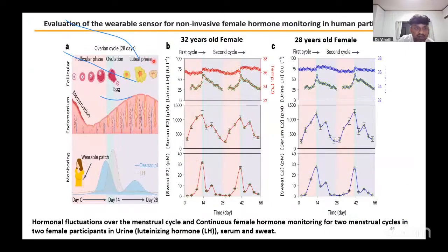Here from the real samples we can identify the growth of female hormone from menstruation to ovulation and the luteal phase. Here are a 32 year old female and a 28 year old female. Here we can see that in 14 days the hormonal level was very high, and then it was decreasing, and then after this is a second cycle. After the second cycle, around 40 to 42 days, it shows the highest estrogen hormonal levels. Here it might be due to the ovulation.